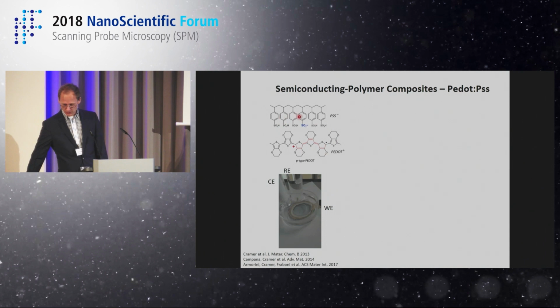These are so-called semiconducting polymer composites. The semiconducting polymer is actually this part here. You see, it's a long polymer chain made of aromatic molecules just connected one to the other. And the nice property of these molecules is that once you have a positive charge inside such a chain, due to the pi system that is delocalized along the whole chain, such a charge can be transported all along the polymer chain or also hop from one polymer chain to another.